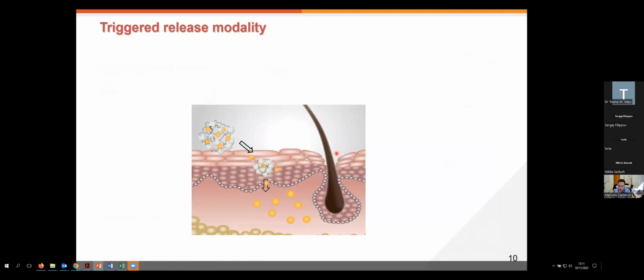And for instance, NIPAM, isopropyl acrylamide, has been used and studied a lot for several decades. So we know that this polymer has a transition of around 32, 33 degrees approximately, depending on the methodology of synthesis and copolymers we use. And it happened that these sorts of polymers are especially